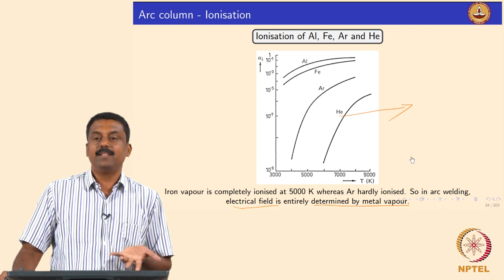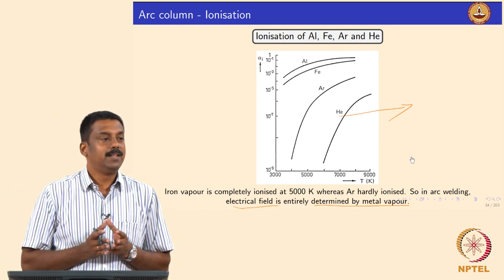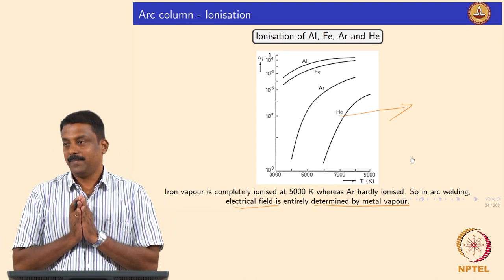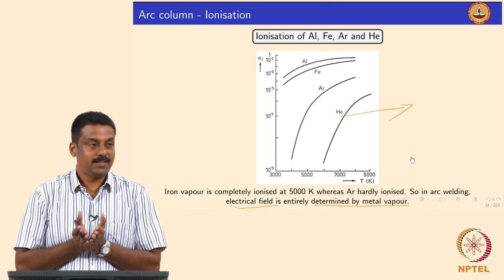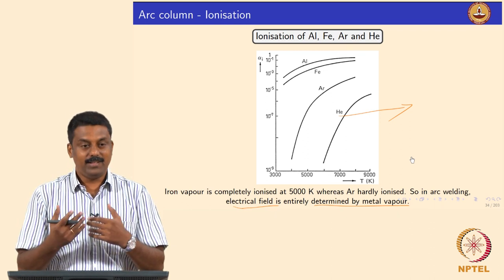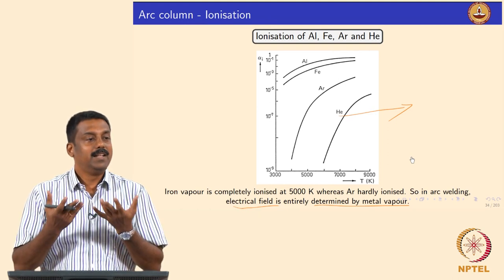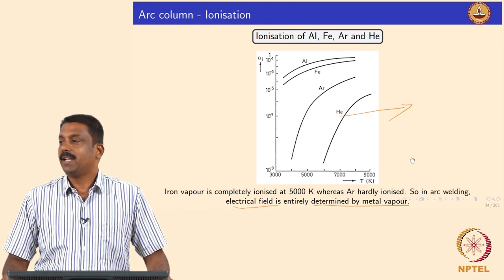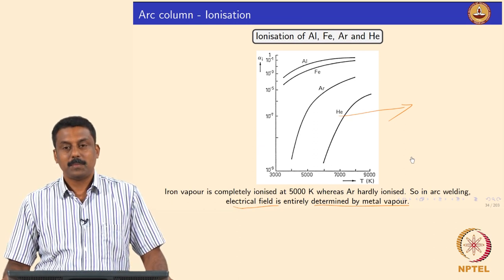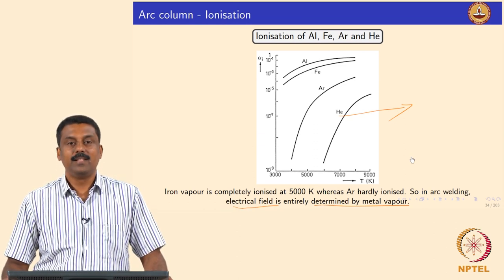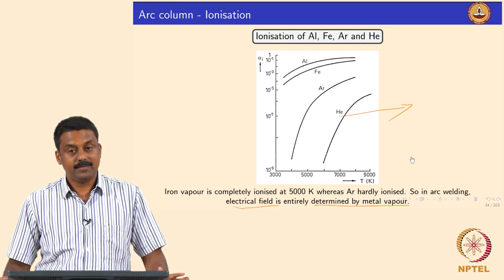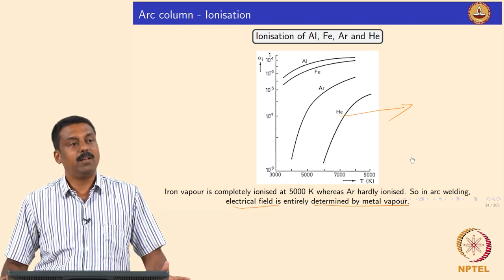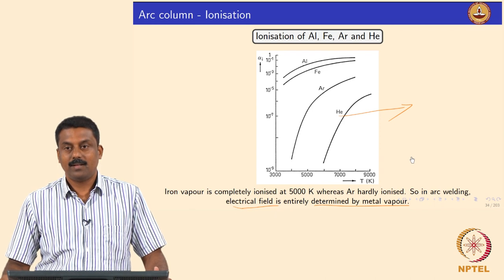The lesson here is: when you have gases with very high ionization energy, your arc temperature will also be high. If you want to ionize the inert gases, you need to supply more energy, and that can happen only at higher temperatures compared to gases with low ionization energy. This is extremely important in welding because it determines your choice of shielding gas, and the arc temperature is also determined by the metal vapor generated.